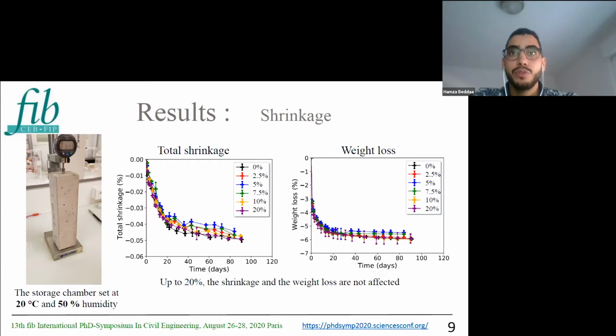Show that replacing up to 20% of coarse aggregates by shells doesn't affect the concrete drying shrinkage evolution. And the weight loss over the 3 months has also been measured on the same prismatic samples, and the result of this parameter is coherent with those of the shrinkage. So there is no effect up to 20% of substitution. This finding can be attributed to the use of the same water to cement ratio and the same mortar volume fraction for all concretes.